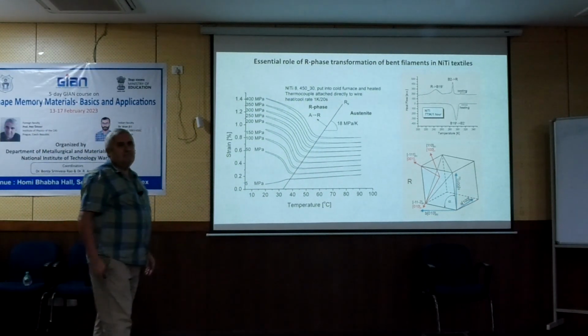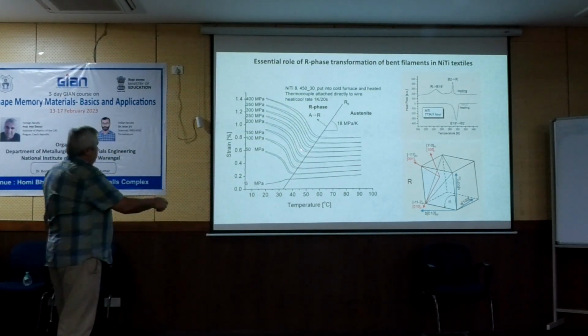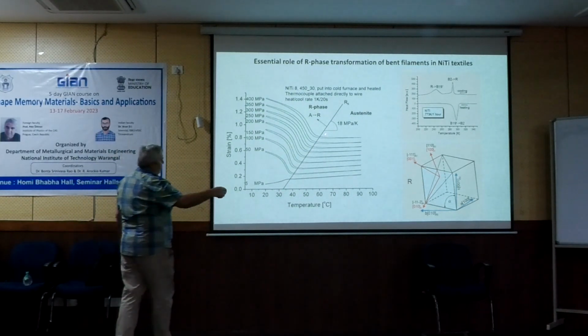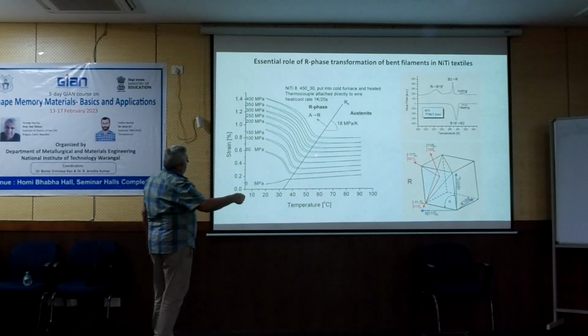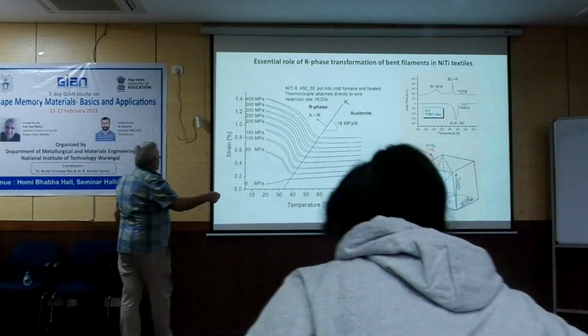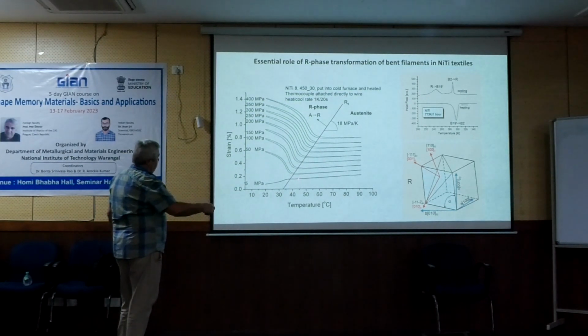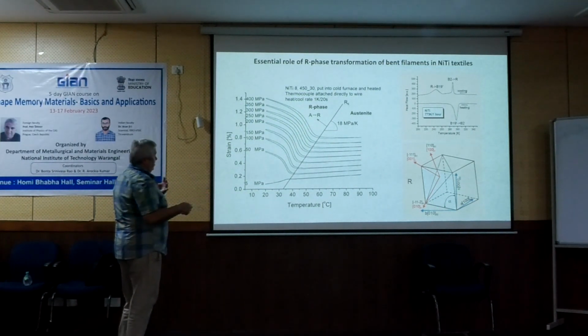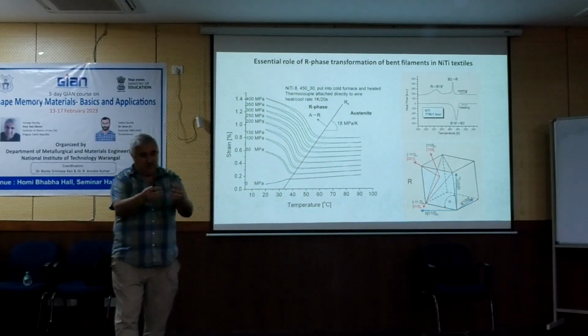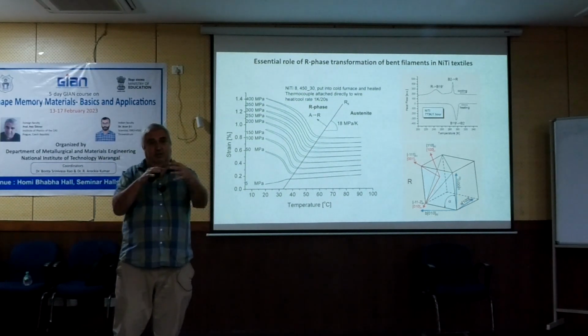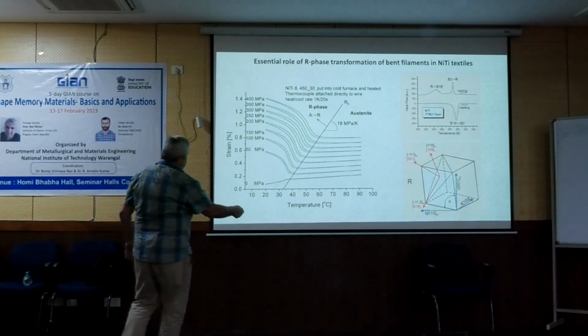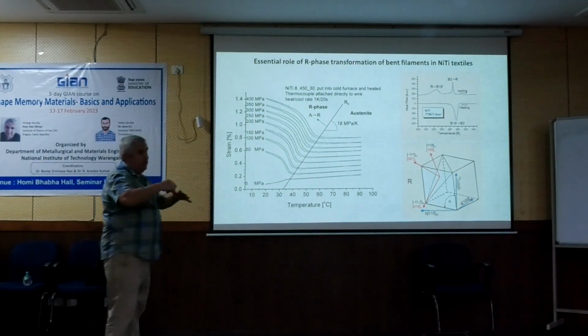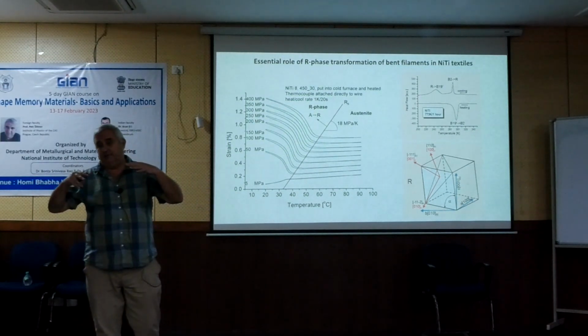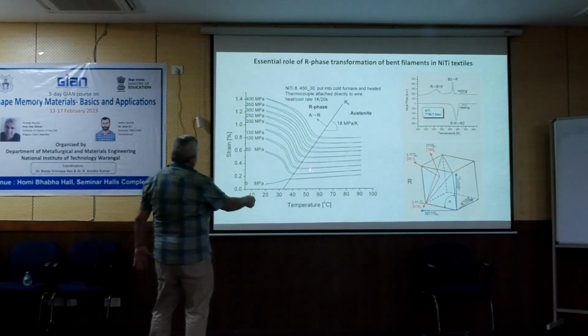But stiff, do you mean it becomes like a sheet of metal, or how stiff does it become? No, because with this R-phase, we had to test the wire exactly. So around in this range of temperature, the R-phase transformation starts at some stress; here it starts at 60 degrees, here at 40 degrees, and you have this strain of about 1%, which is due to the R phase. So you can deform it in this 1% range if it is in the R phase. But if you heat it up to 100 Celsius, this strain will not be accessible, and it becomes perfectly stiff. Once you decrease the temperature down to 50, it becomes flexible.